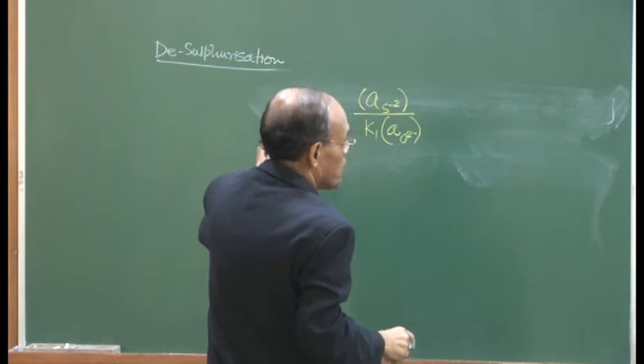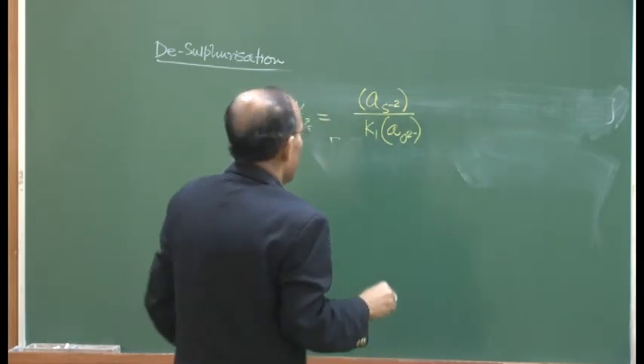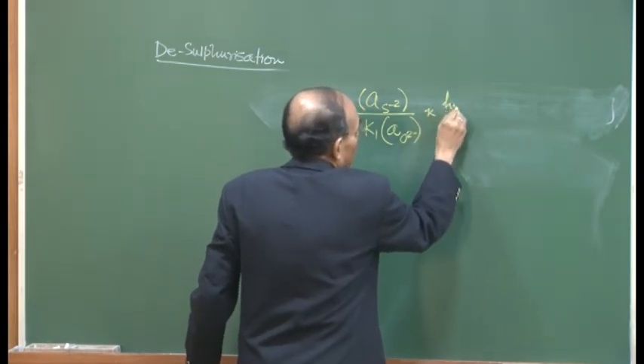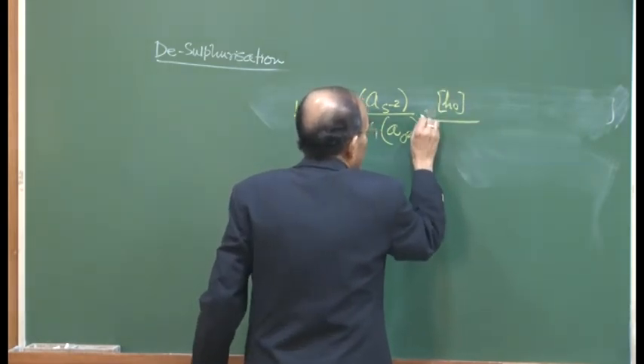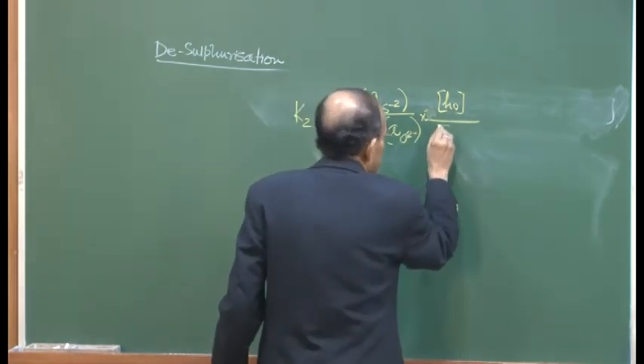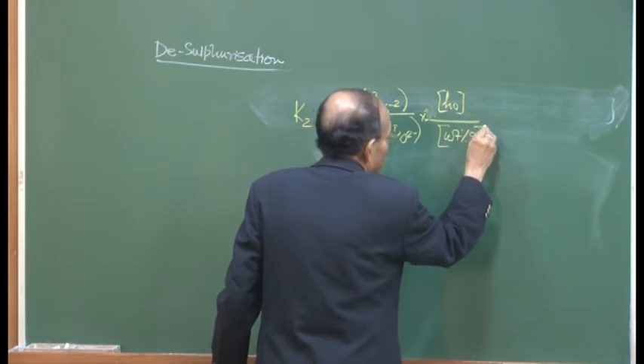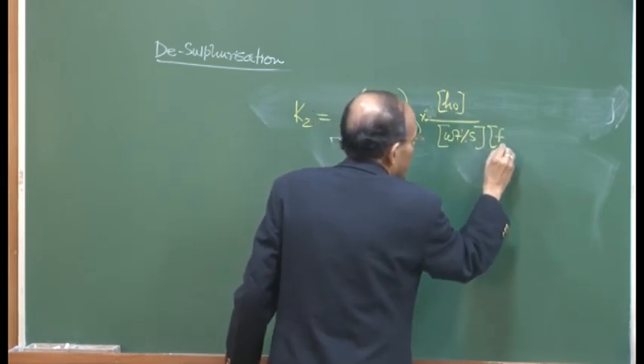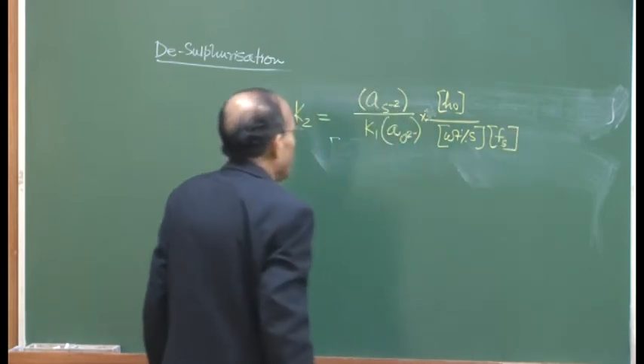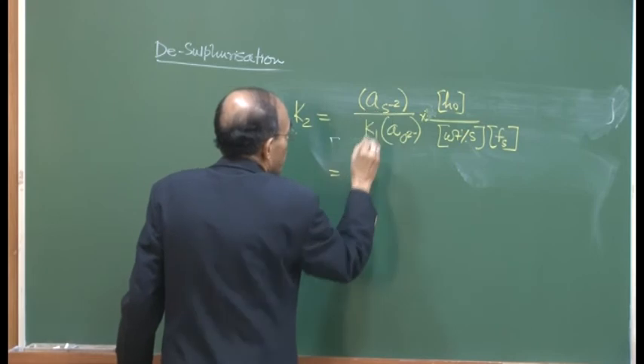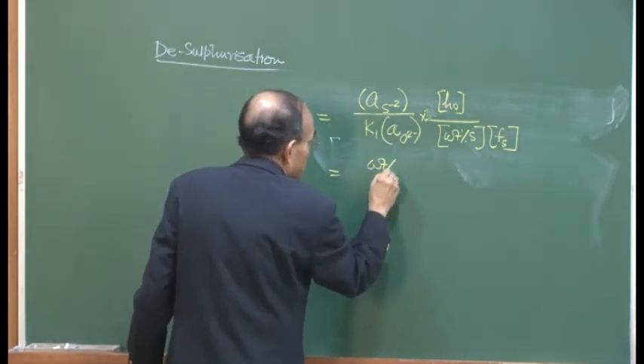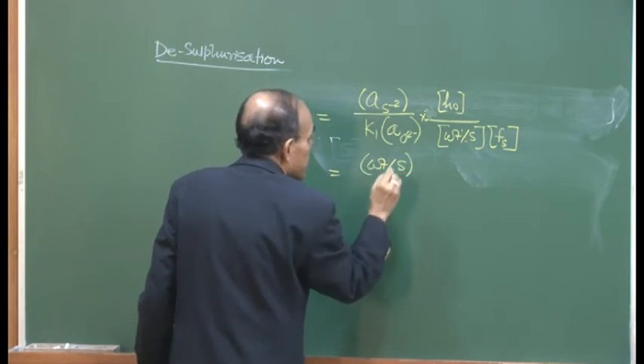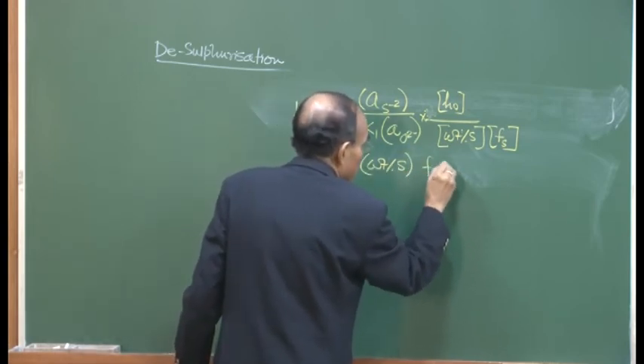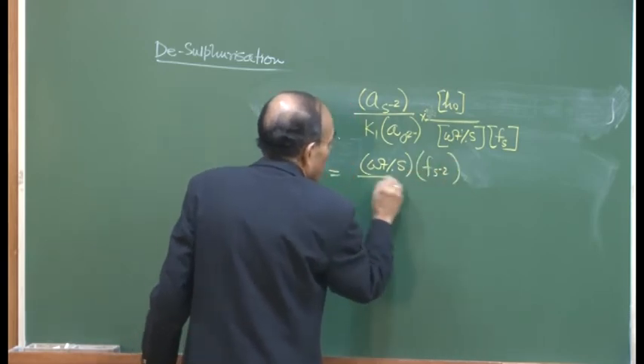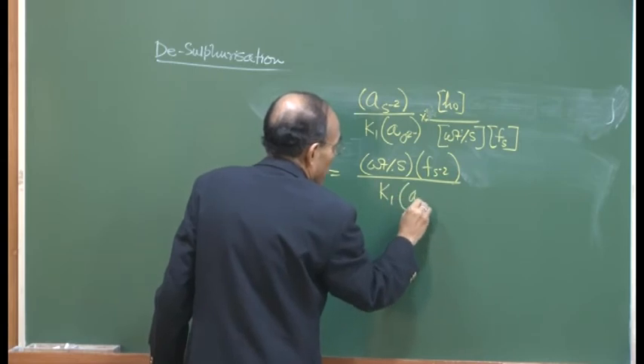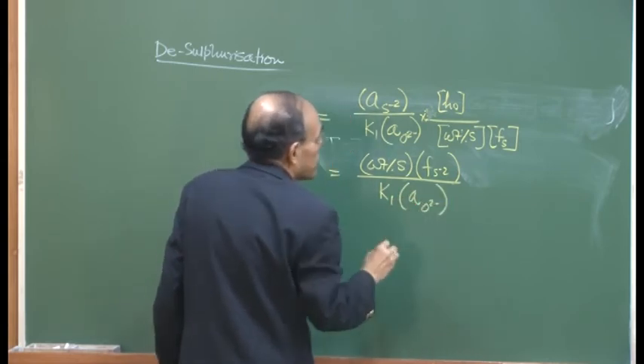So, we have substituted in place of this, and then we have HO divided by what? HS. So, weight percentage sulfur into activity coefficient of sulfur. And we have seen that this is going to be equal to AS2, I have written in terms of weight percentage sulfur, that is in the slag phase, multiplied by FS2 minus, the activity coefficient, and this is K1, AO2 minus into HO.